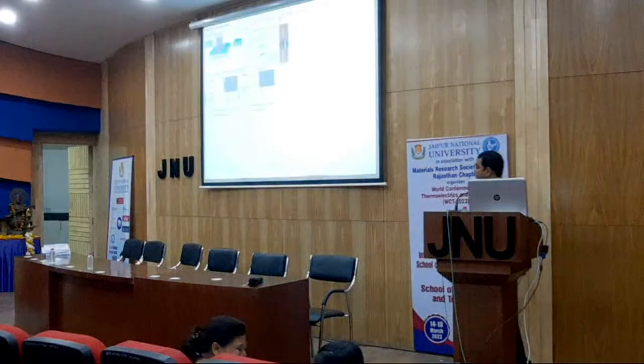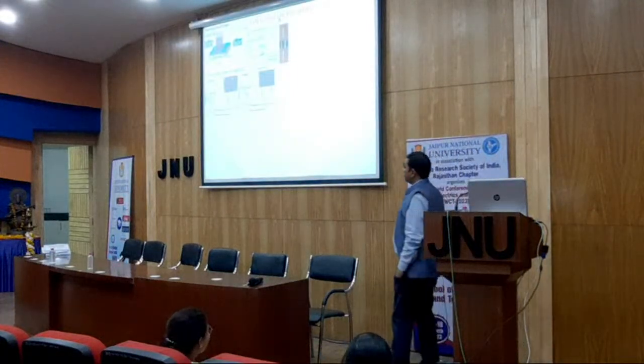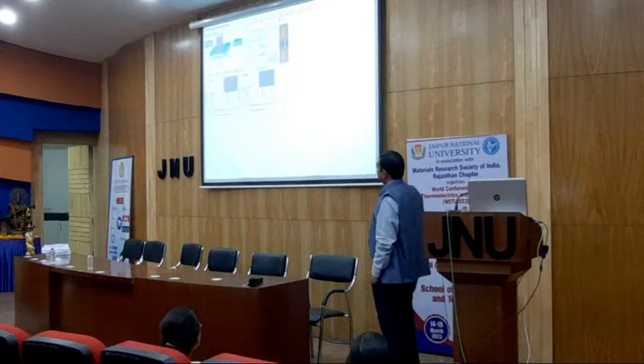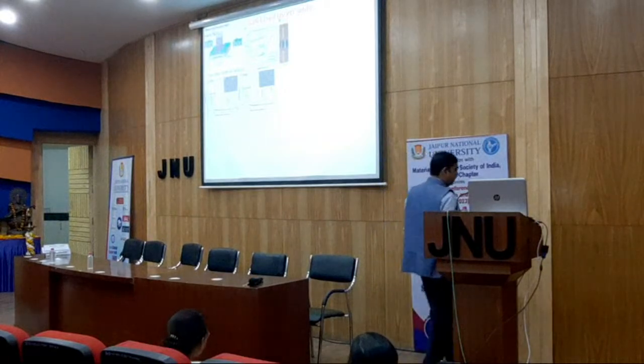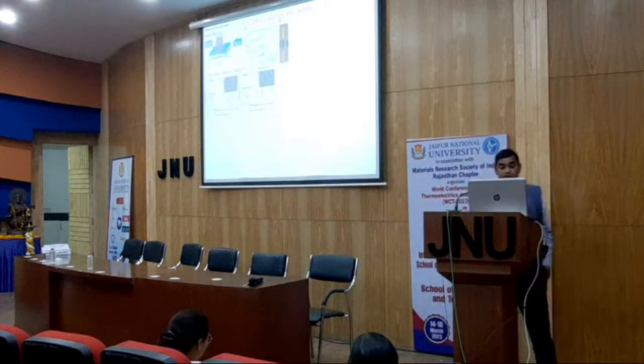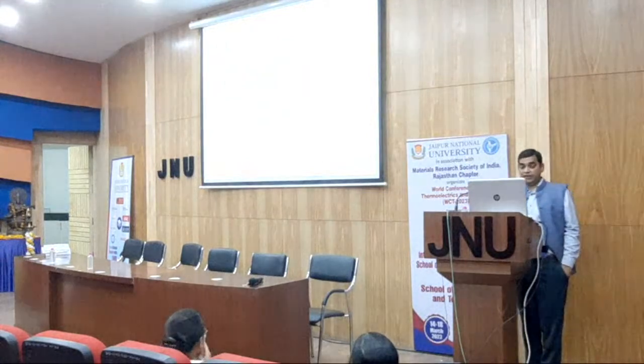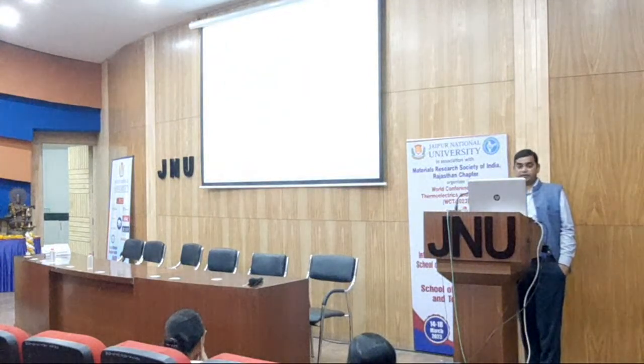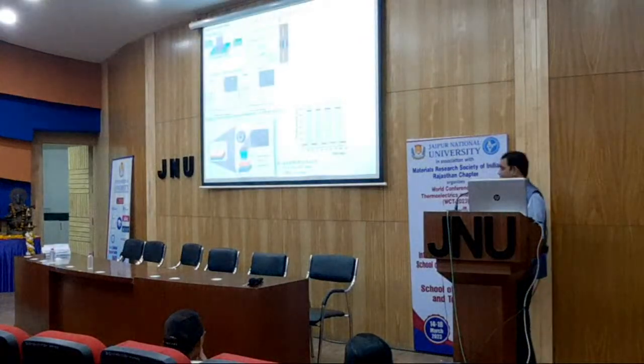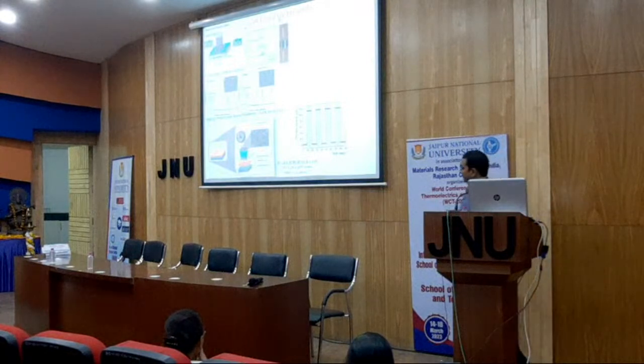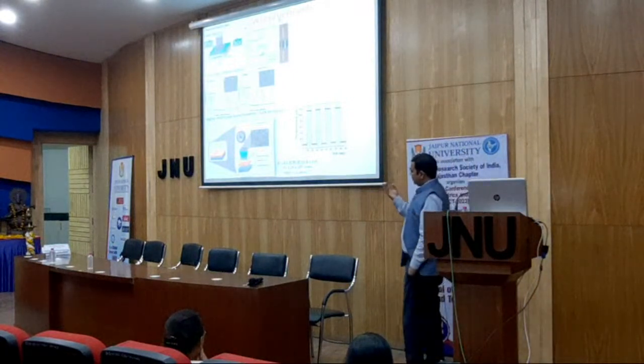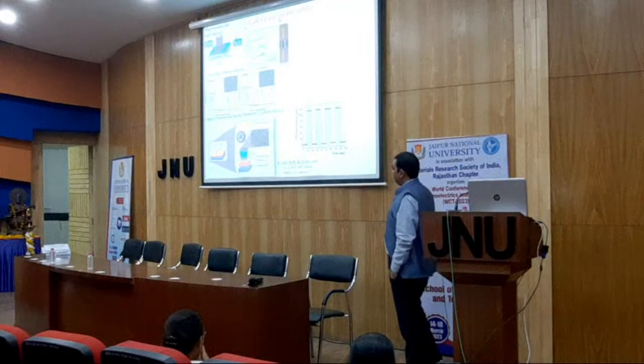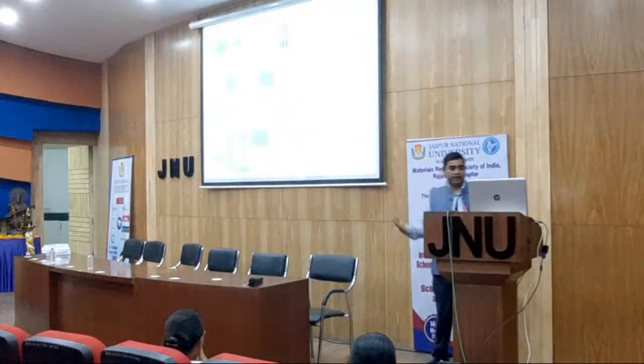Then slowly growing the film. Because of dislocations, you can see these films are not complete. These are 50 nanometer or so thin films. If you increase the thickness, then only the films will start completing. And then these dislocations which were going through the film, we have tried to accommodate and utilize as a template to grow nanoflowers, to increase the large surface area.